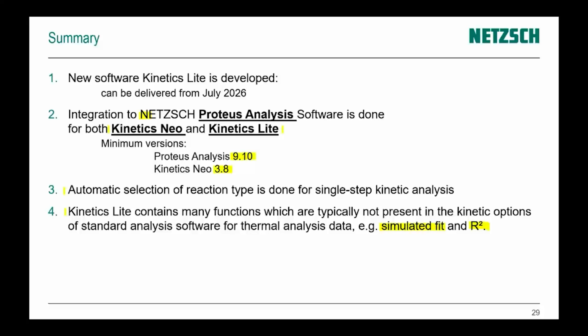Okay, thank you. The next question, how do you find the pre-exponential constant A? Can you tell us more about it here? Yes, for nth order kinetics, we can calculate the pre-exponent according to the best fit. The software will find the pre-exponent and activation energy to have a best fit of simulated data with pre-exponent and activation energy and our experimental data.